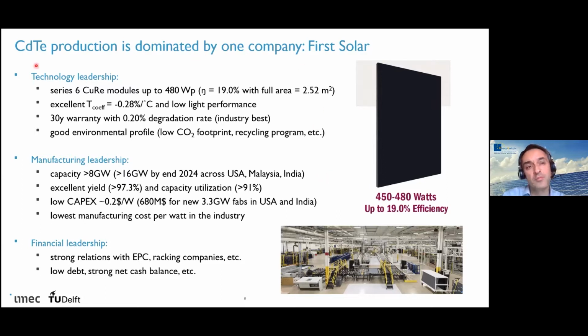And what is typical for cadmium telluride is that it really has the lowest manufacturing cost per watt in the industry. So actually the cost is lower than, for instance, for crystalline silicon. The main downside that this technology has is twofold, I would say. They're using cadmium, which is a toxic material, so people are a bit skeptical about that. But the main downside is that they use tellurium, which is a very scarce material. So we will never be able to produce this material in the same quantities as, for instance, crystalline silicon because of the scarcity of the material. But you can reach very high efficiencies with this material, and it is at very low cost. So that's why it also has still a relevant market share.